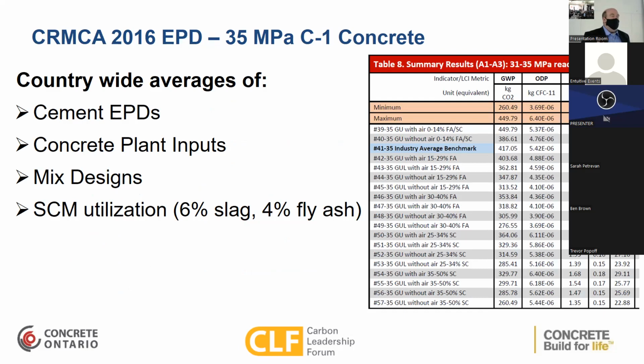What we basically were doing was averaging every cement EPD, cement plant EPD, from coast to coast. We calculated the concrete plant inputs for all 7 regions and then averaged them together. Then we took the mix designs for all 7 regions, averaged them together, and came up with this harmonized garbage that really doesn't tell you much.